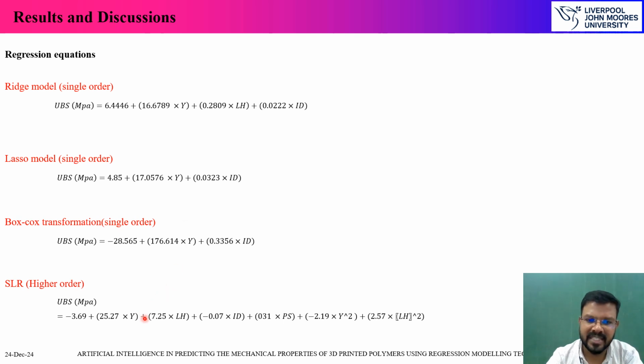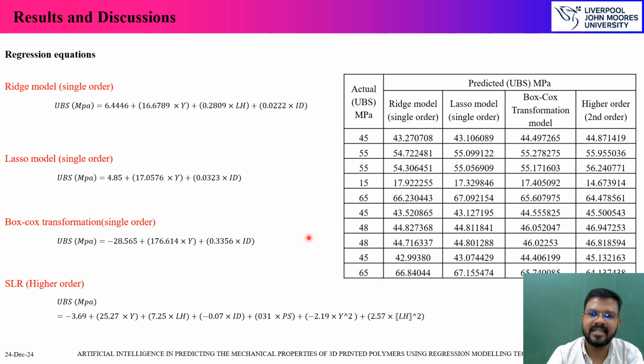This is where we get to see the order to the power of 2, that is layer height to the power of 2, followed with Young's modulus to the power of 2, having the negative coefficients and then the positive coefficients here. And the intercept value for the higher order polynomial equation is minus 3.69. With these equations being used to predict the ultimate bending strength, this is our result.